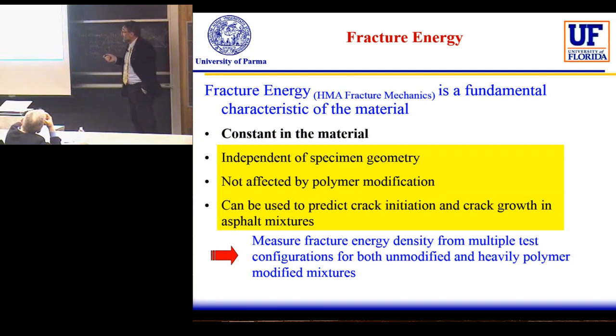The second step is to verify that fracture energy is independent of the specimen geometry, so independent of the stress field behind the crack initiation, and that it was not affected by this big change in the mechanical performance of the material. Bitumen is a viscoelastic material, but by adding polymer we increase the elastic part a lot, so we are changing the mechanical behavior. So it was not so clear that the change was not affecting the hypothesis of the HMA fracture mechanics, and the other hypothesis that can be used to predict the crack initiation.